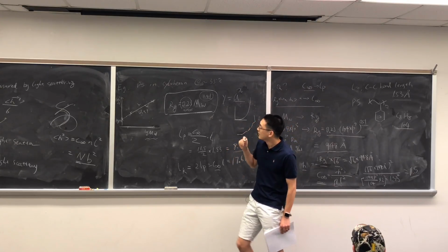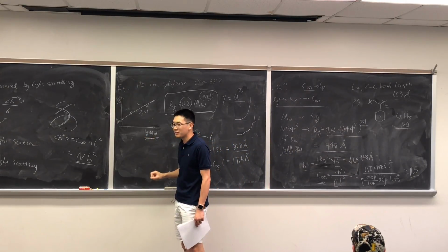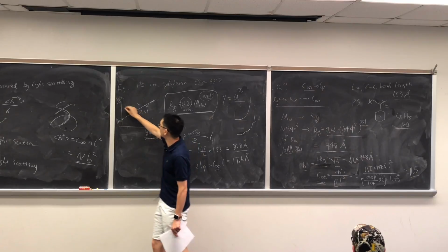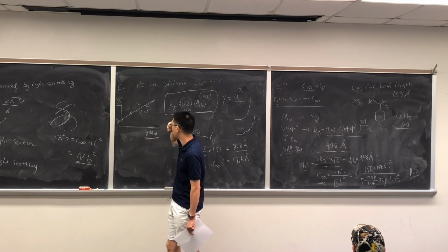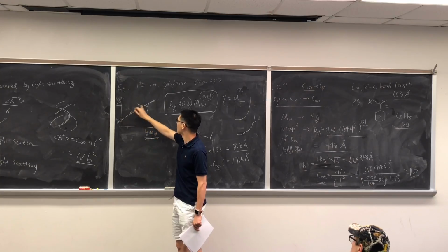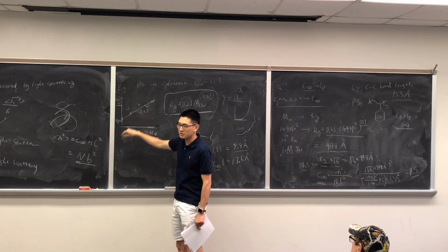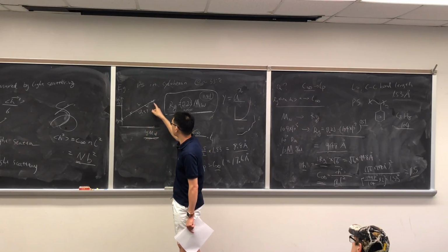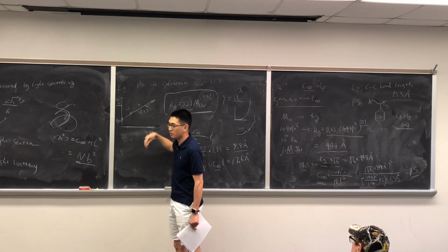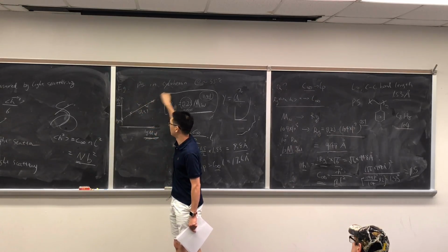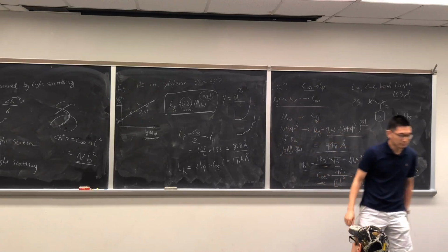Just do a very simple measurement: measure the molecular weight using GPC in your lab and do light scattering to measure the radius of gyration for different molecular weights. And typically we do several data points because you need to get relative statistics. If you only measure 3 or 4 data points, your curve tends to be off. So you measure a couple of points and then get this generalized relationship. Okay?